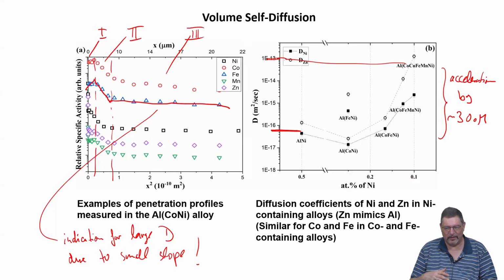And it again shows there is a variety of different behavior which we find for the different high entropy systems, going again from slight deceleration, in one case a little bit more deceleration, but also going to acceleration, just depending on which specific high entropy system you are looking at. In all cases, it's the same configurational entropy contribution which is taken into account. And that, I think, shows very nicely that there is no high entropy, or at least no high entropy related tendency of how diffusivity would develop in a specific alloy system.